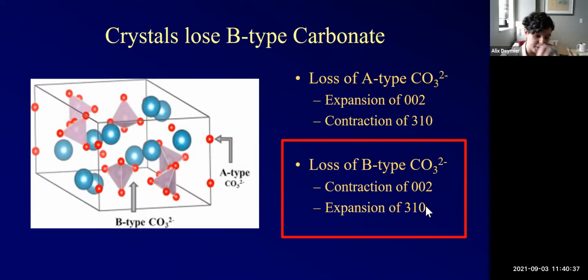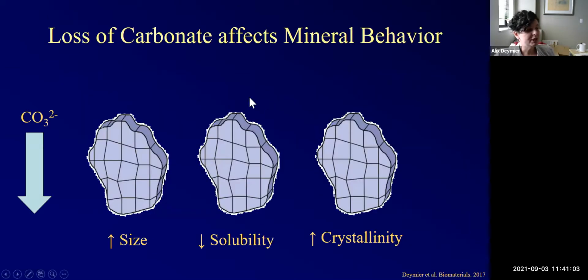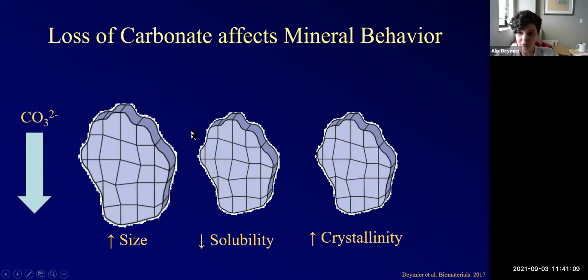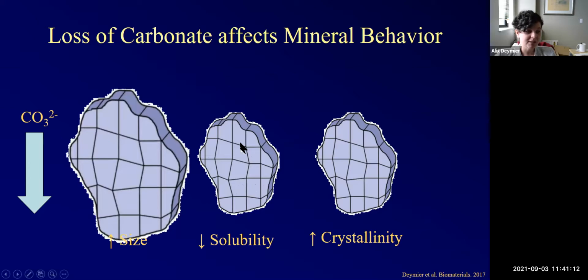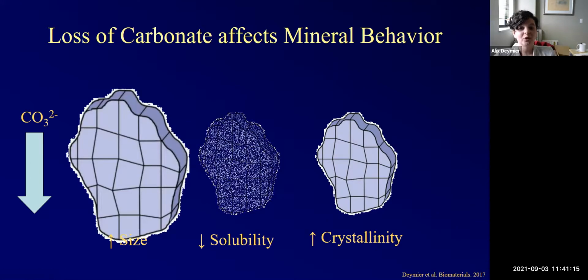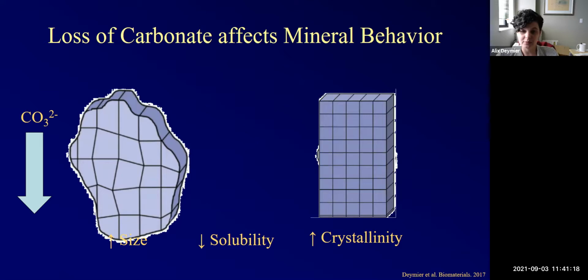So we know that by putting these types of crystals into acidic solutions, we're actually removing carbonate specifically, not from the surface of these crystals, not from the A location of these crystals, but from the B location of these crystals. Now, again, why is this important? Well, because we've done a lot of research on the effect of B-type carbonate on crystals. We know that if you decrease your B-type carbonate, that will tend to mean that you have an increase in the size of the crystals, that you have a decrease in the solubility of the crystals, and that you have an increase in the crystallinity of the crystals.